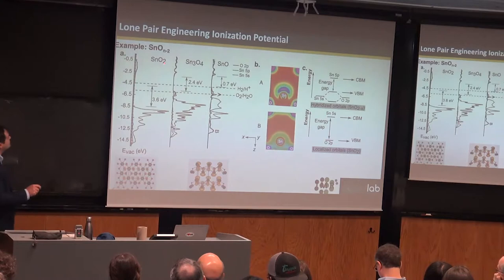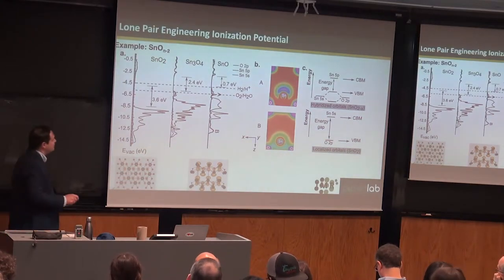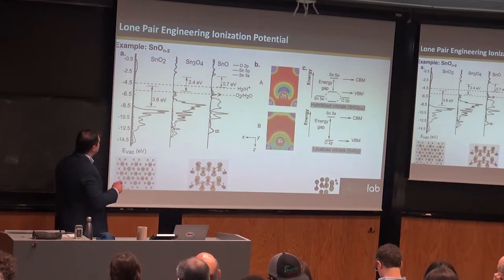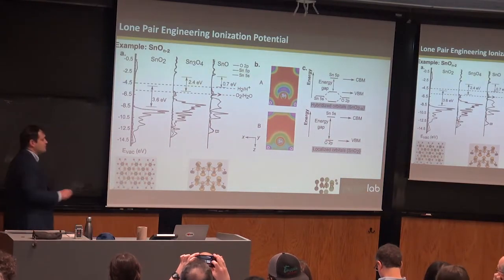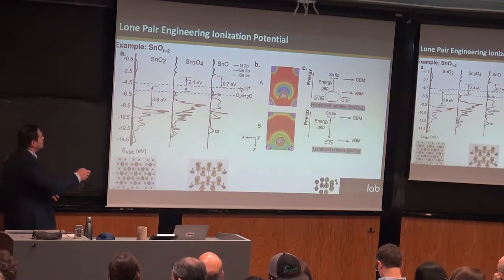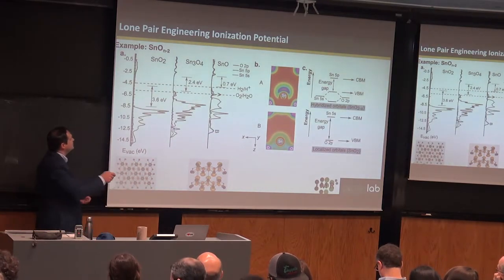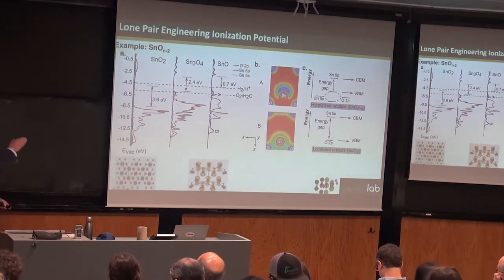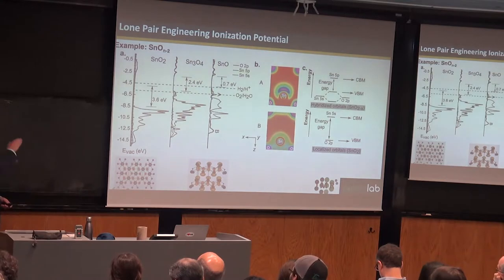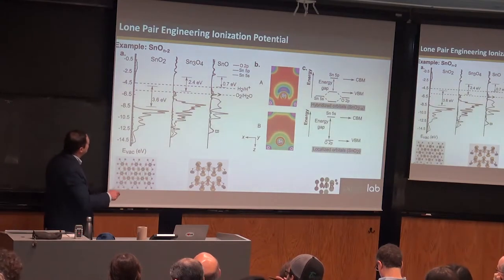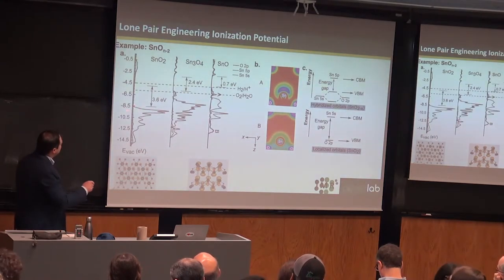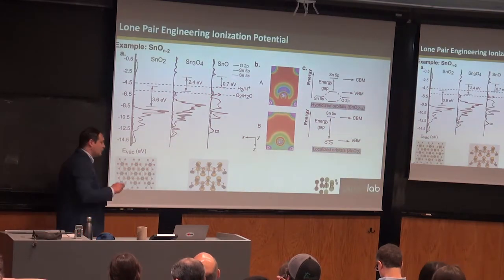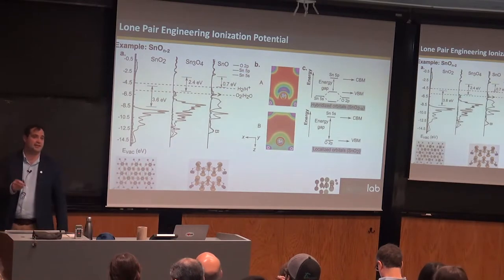So if I take a system like 4+ and 2+, the idea is that you can change the ionization potential by having a mixture of 2+ and 4+. So to form Sn3O4, there's a whole host of possible metastable phases in between these two, by taking tin dioxide and cutting planes, cutting oxygen out in regular planes along the 110. So this is a candidate for that, where the idea is you go from this oxygen-derived valence band edge, and then you're introducing these lone pair states, the antibonding states associated with it, and so you can raise this up. In the case of tin monoxide, you go too far. You actually get a narrow band gap material.